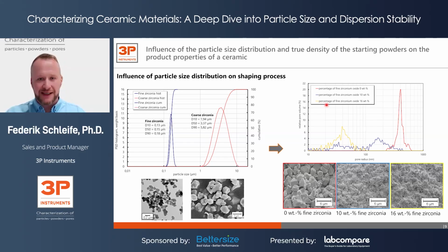But finally, when you mix 16 weight percentage of the fine zirconia into 84% of the coarse zirconia, you achieve a green body density with only a monomodal pore distribution of around 35 to 40 nanometer. So therefore, you can see that depending on the mixing ratio, and therefore depending on the final particle size distribution of the mixture, you can achieve different pore radius and therefore affect dramatically the performance of the shaping process.